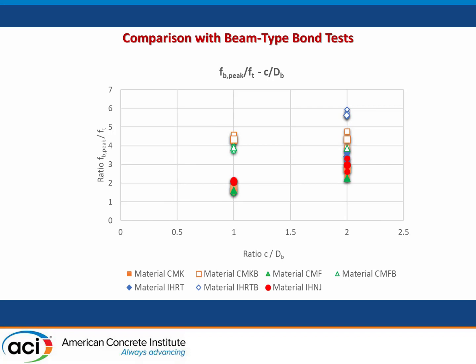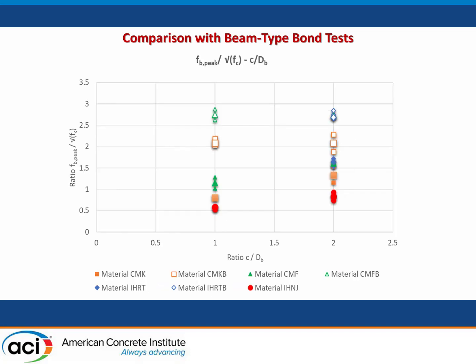The empty symbols in this figure represent the bond stress. The vertical axis is the bond stress divided by the tensile strength of the material obtained after dog bone testing. The horizontal axis is the ratio of the clear cover divided by the bar diameter. The empty symbols are those obtained from beam tests. The filled symbols are those obtained from identical mixes from tension pullout tests. You see that the beam tests are systematically well above the tension pullout tests, leading to an overestimation of the bond capacity of the reinforcement.